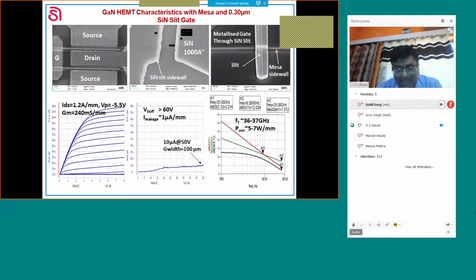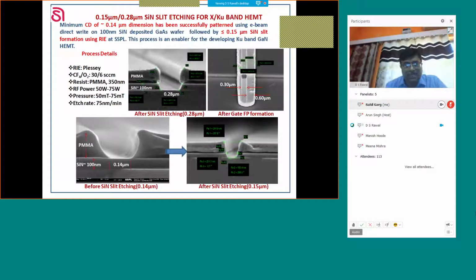So we have fabricated devices using this technique, and the cutoff frequency measured is of the order of 36 to 37 gigahertz with power output of 5 to 7 watt per mm. And now we are working on 0.15 micron devices. Again, the same process is used, but we have now defined the electron beam lithography dimension of 0.14 micron. And then through this 0.14 micron, we need to remove silicon nitride selectively, which has already been done. And then metallization is done. In this way, we are able to reduce my gate length to 0.15.